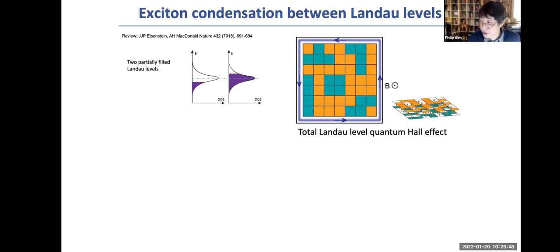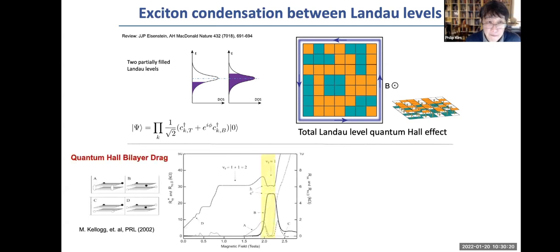Now, this is hand-waving arguments, but you can go through a complete, accurate mathematical structure. If you write down the coherent wave functions that describe this complementary filled Landau level, where the correlations start to happen, in fact, this macroscopic wave function exactly follows the wave function that you expect to see in the exciton condensation state. And that's basically the way that we can create an exciton condensation-like state by just using the magnetic field. In fact, this type of experiment was done in semiconductor heterostructures almost 20 years ago.